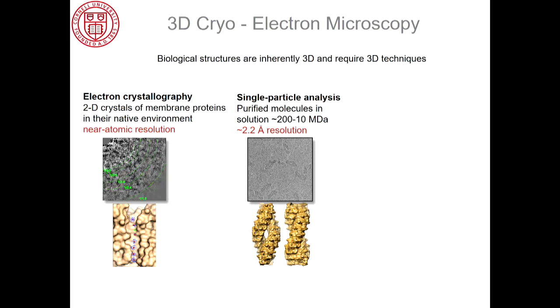The technique that really wins out today is single particle analysis, and by single particle I mean hundreds of thousands. But what you do is you take an image where each image has a very low dose per molecule, and then you average over hundreds of thousands of molecules to reconstruct in 3D the object you're looking at.